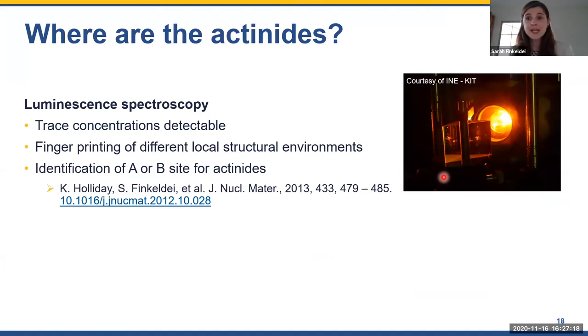Okay, so once we had a pretty good understanding about the structure and the physical properties of the pyrochlore structure, we were interested in studying if the actinides can structurally be uptaken by a pyrochlore structure. So what I did is I performed luminescence spectroscopy experiments. And the beauty of this technique is that you can really detect trace concentrations. So you can just use 10 ppm of curium in your sample, and this technique is sensitive to such low concentrations. And you can then probe the local structural environment of your dopant of interest.